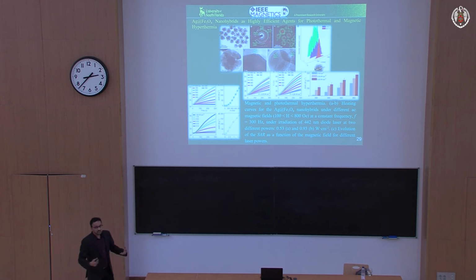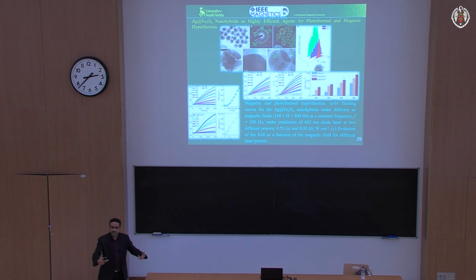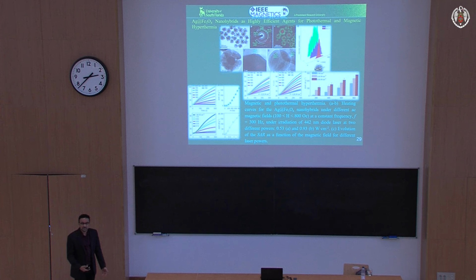So in this case, we can actually try two things. We can apply a laser, we can apply an AC field. You can also shine a laser in combination to give you faster heating. So that's the reason for these hybrid nanoparticles. And yeah, we achieved this. We were able to show that SAR can be increased by combining both these types of heating.